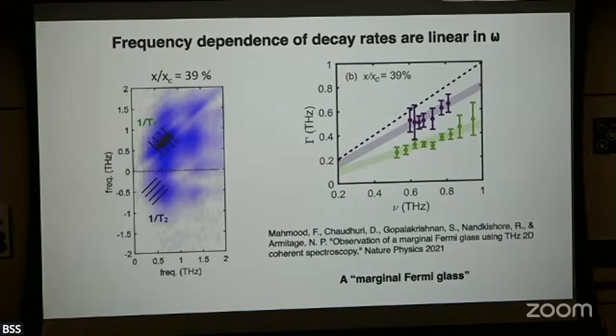So the fact that the rate goes to 0 in the figure, is it a signature of this Coulomb gap? No, not directly. The Coulomb gap is something a little bit different. The role of the Coulomb gap in an AC conductivity experiment, I think, would be controversial. The Coulomb gap is something that you would see in the n+1 or n-1 spectral functions, so in the electron addition or removal spectrum, and not in an optical response. So it's a charging gap essentially, right? It's the response to taking charge out of the system and the energy cost it takes to beat the long-range Coulomb interaction.